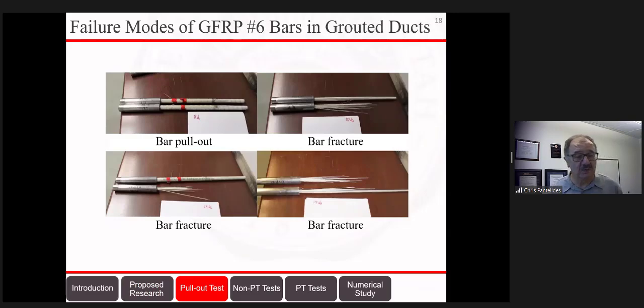So as we predicted, there was a point where the bar pulled out if the embedment length was very short. And then we found out there was bar fracture, which is the desirable mode of failure. And we determined that 14 bar diameters were actually more or less an acceptable length. And we use a much higher embedment, of course, in our experiments than this. Much more research, of course, is required on this front, and these were just some preliminary tests, but we knew our columns would work.